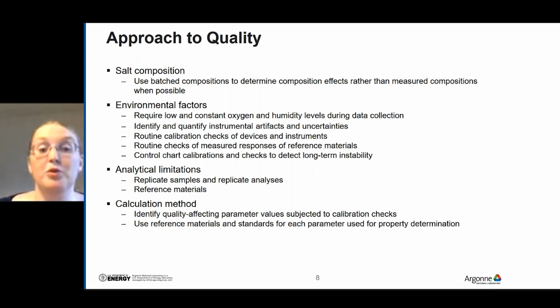We do routine checks of measured responses with reference materials, particularly for devices that we cannot measure the individual artifacts. We can check their overall response with a reference material. And of course, we control chart all of those calibrations and checks over long times to check for instabilities. To limit or minimize analytical limitations, we always perform replicate analyses with replicate samples and then use reference materials to check proper operation. And of course, the most important aspect is being sure your calculation method has been assessed. So that involves identifying each quality affecting parameter and subjecting each one individually to calibration checks where possible, or using reference materials to do so for property determination.